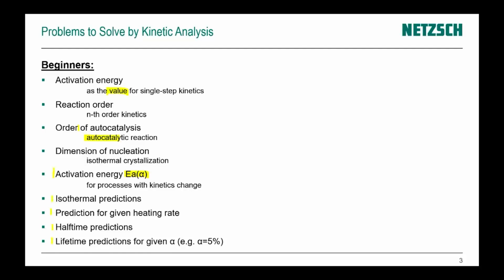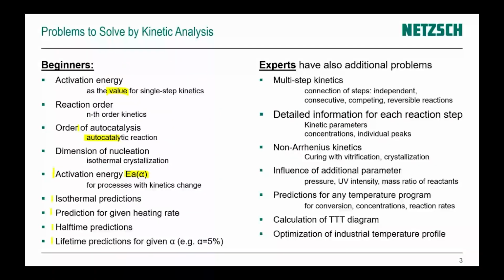And if the degree of conversion or decomposition is higher than 5%, then the material has other properties and cannot be used anymore. And here it is very important to know at which temperature, and at which time, the 5% of conversion will be found. These are really the first problems which could be solved by kinetic analysis for the people who just start to work with kinetics. And if you are an expert, then you have some additional problems.